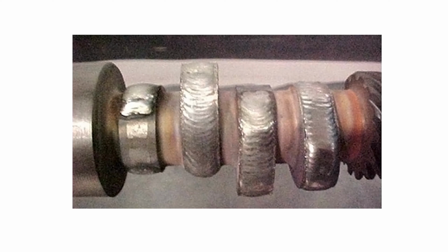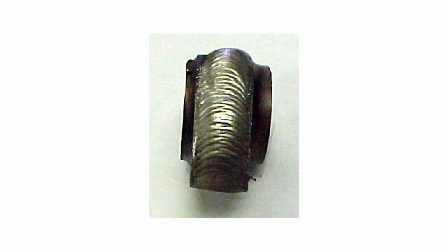And the other trick that we applied to this is something we learned years ago when we were welding NASCAR cams. NASCAR rules limit cam lift, but they don't limit how far you float the valves. So when these engines are running over 4,000 RPM, you're actually floating the valves and getting additional lift. It all is well and good until the tappet lands back on the cam, and when it does, it better land on something hard and wear resistant. This is why we're applying a welding coating to all these camshafts.